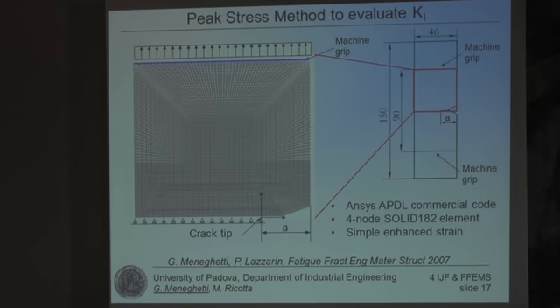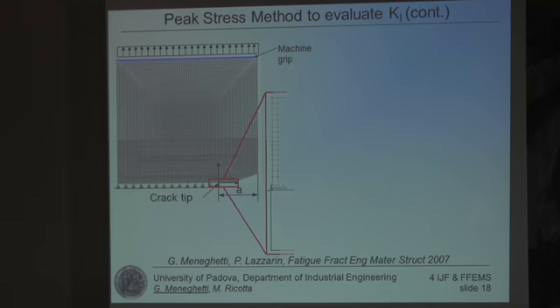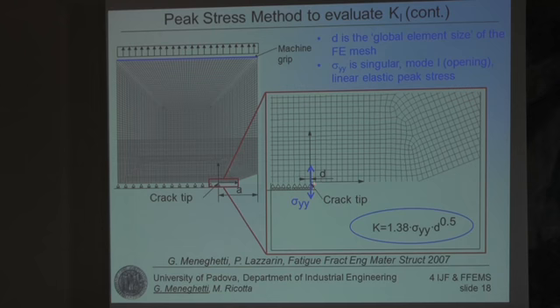If we produce a finite element mesh with a given mean size of the finite elements, in order to evaluate the stress intensity factor right at the crack tip, we need just to evaluate the singular linear elastic peak stress at the crack tip. We need to know the average finite element size adopted in the analysis. If we multiply the linear elastic singular stress at the crack tip by the mean size of the finite element to the power of the stress singularity exponent, which is 0.5 for a crack, and we multiply all this by a calibration constant which depends on the order of the shape functions adopted, we can estimate K with an approximation of about plus or minus 3%.